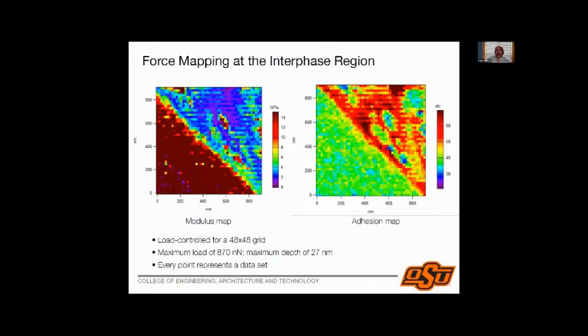And if I know the indentation response, then I can do several things. For example, I can calculate the modulus. So I know the modulus at each one of these points. And what I observe is, if I come from the bulk epoxy close to the carbon fiber, there is an increase in the modulus over here. We look at this data quantitatively rather than just in different images. One of the things that we do is use the adhesion map, which is also generated during these indentation experiments, to figure out exactly where the carbon fiber lies. So this is the same image. You're looking at the adhesion map. The adhesion with carbon is very low. Adhesion with polymer is very high. So you can figure out exactly where the carbon fiber interface lies. And each one of these points represents a data set.